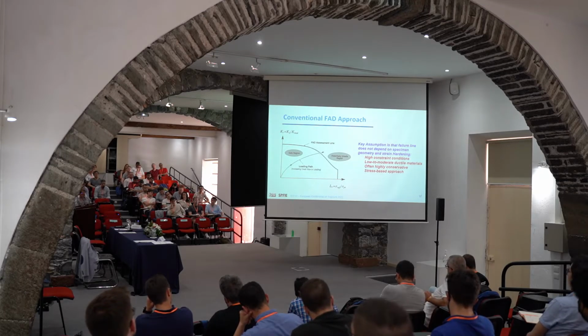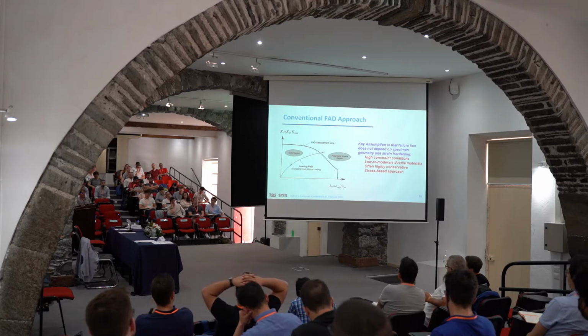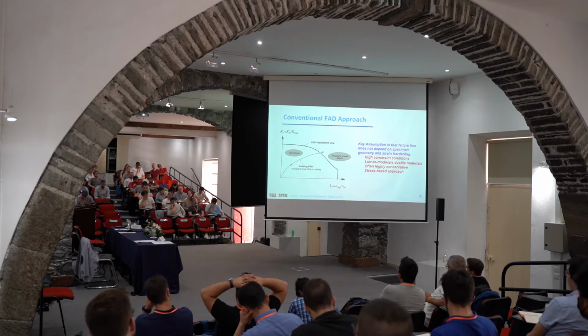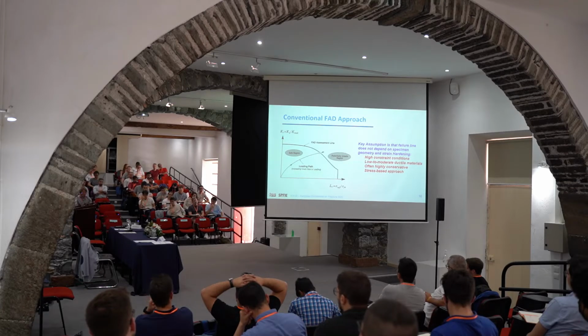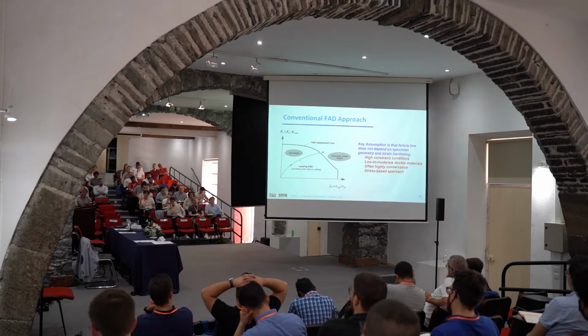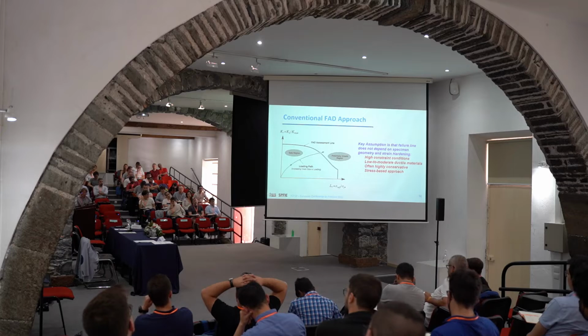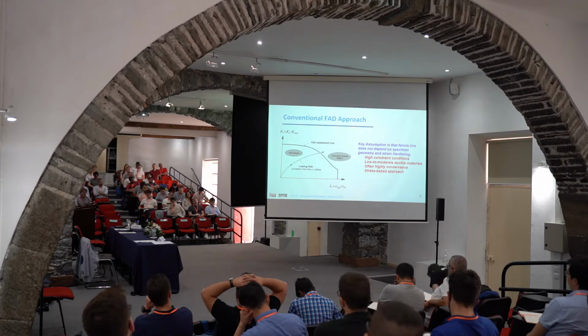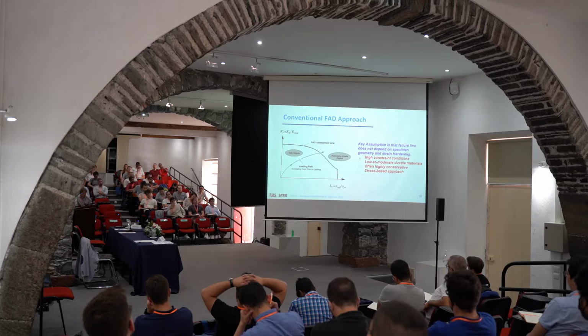And strain hardening. If you saw composites this morning, of course, you wouldn't be worried about strain hardening. But in metallic materials, we have to worry about strain hardening, which is the regime after yielding. Depending on the plastic flow behavior, the material has less hardening or more hardening. So strain hardening is a very important parameter for fracture mechanics.